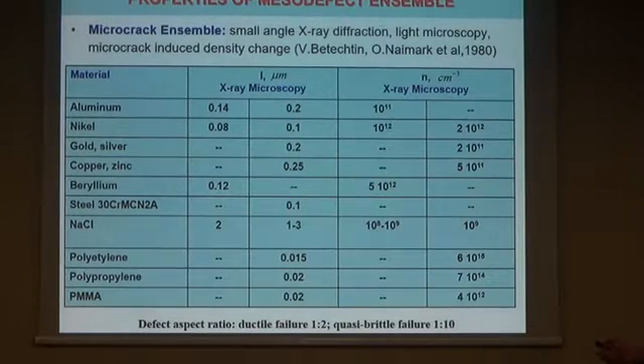First of all, I would like to point out that more than 30 years ago in Russia, due to small-angle X-ray diffraction study, very characteristic features of the transition from damage to failure were established from the point of view of collective properties of typical defects like microcracks and microshifts. You can see typical concentration, characteristic size, and typical aspect ratio.